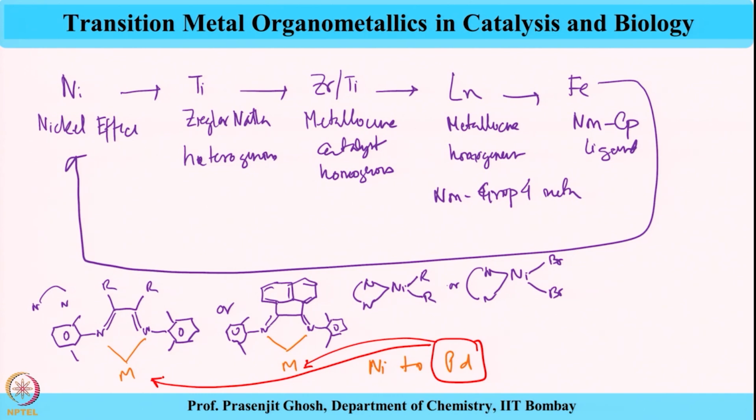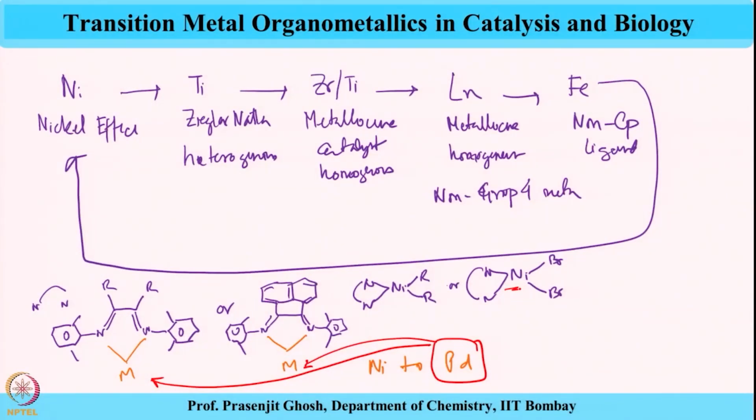This is really interesting, because olefins with functional groups poison the catalyst, and such copolymerization with functional monomers was a real tough challenge at that point of time. This was overcome by substituting nickel, which happily did ethylene polymerization or ethylene alpha olefin copolymerization, with palladium, which could carry out ethylene polymerization with polar functional monomers. So, this is a very interesting story.